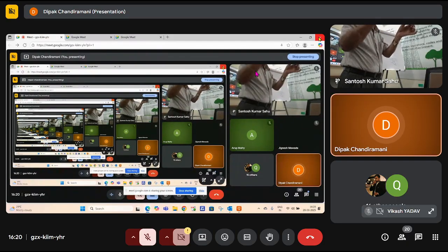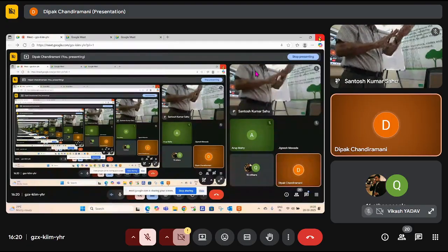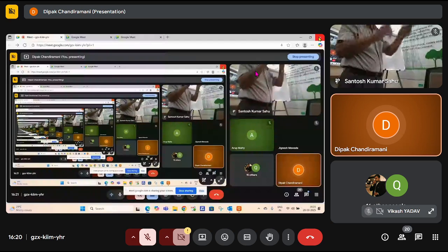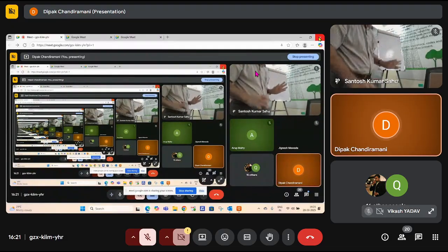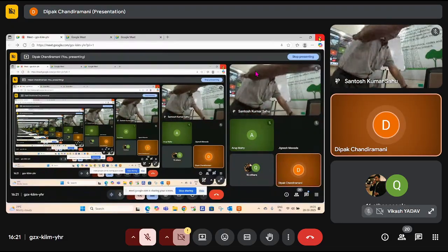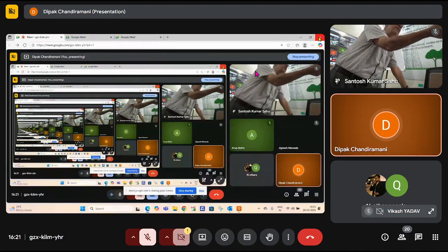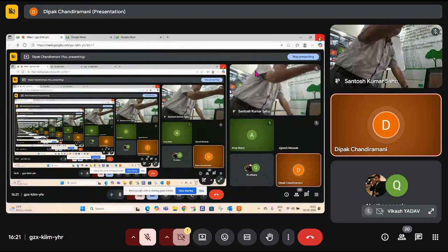So I put a micrometer, I measure the thickness, I put my gauge there after doing all the calibration on the machine. Now I take this validation piece, put the gauge there, check whether it is showing correct, more, or less, and make correction. Then I am sure. And the piece should be equal or near to the nominal thickness of what I'm trying to ascertain. So it should ideally be made of the same material. We take one reading there, and you check it with the micrometer, and you are okay.